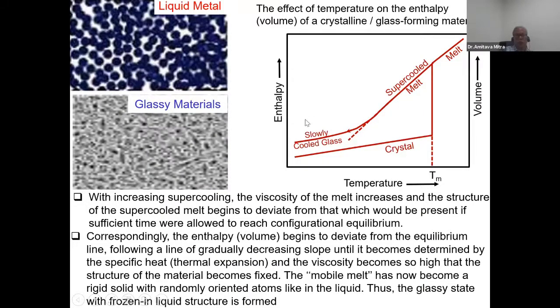Because of the viscosity of that liquid, there will be a restriction. The viscosity will be so high that the atoms cannot move, and they are randomly frozen in the liquid. So we are preventing crystallization, randomly orienting the atoms through this supercooling, and because of this viscosity process, the atoms are randomly oriented, giving us a glassy material instead of a polycrystalline material as told earlier.